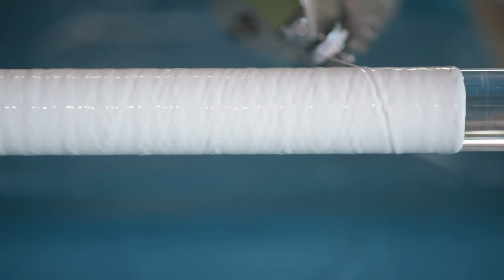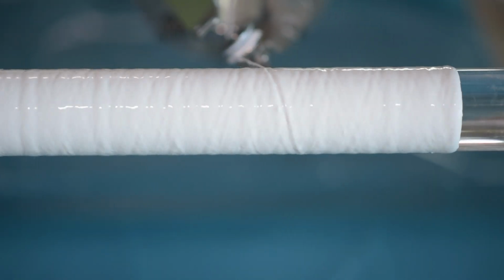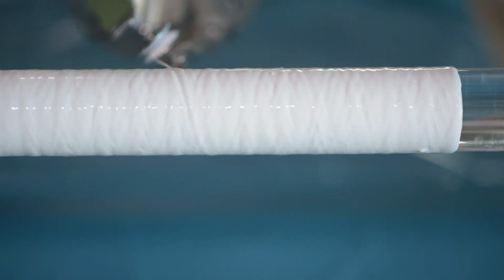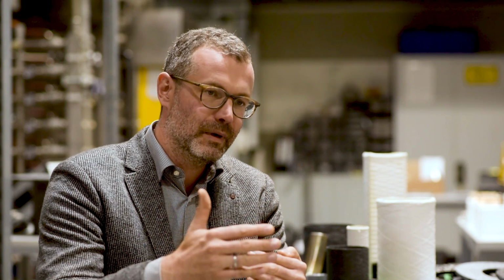To achieve weak interface composites, all the ceramic fibers were previously coated. Normally, the coating is necessary to protect the fiber against corrosive attack during the later application at high temperature or during the process of manufacturing. And the other thing is that the coating is necessary to weaken the bonding to the matrix, so that you really have a weakened interface between the fiber and the matrix.